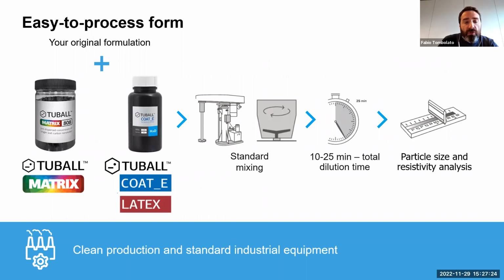To achieve properties from graphene nanotubes, it is important to understand the mechanism behind them. Graphene nanotubes bring electrical and thermal conductivity and can improve the mechanical properties thanks to the 3D network that they can build inside the polymer matrix. And to build this 3D network of nanowires, dispersion plays a crucial role.